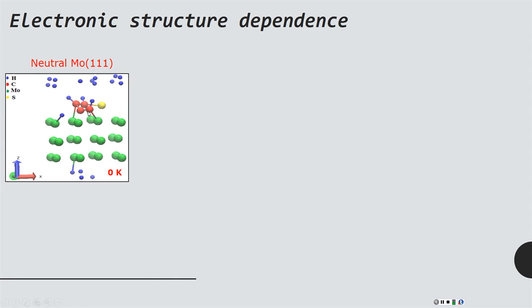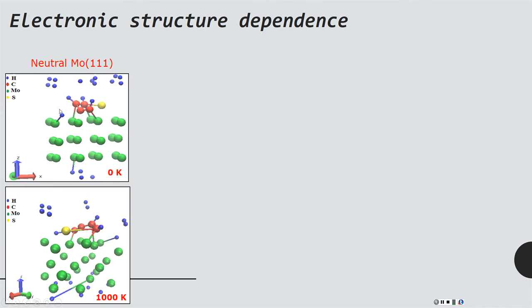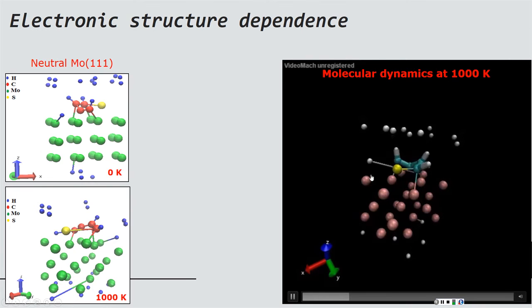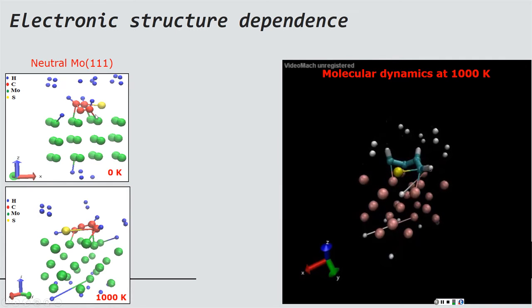Here you can see a thiophene molecule adsorbed on a neutral molybdenum surface at 0 Kelvin. At 0 Kelvin, only one carbon sulfur bond is dissociated, and when the surface temperature is increased to 1000 Kelvin, even though this carbon sulfur bond is elongated, it is not completely dissociated. This movie illustrates the dynamics of this thiophene molecule adsorbed on the neutral molybdenum surface at 1000 Kelvin. At 1000 Kelvin, this carbon sulfur bond is not dissociating completely. That means this sulfur is not removed from the hydrocarbon, and the surface is not catalytically active to remove this sulfur contaminant from this hydrocarbon fragment.